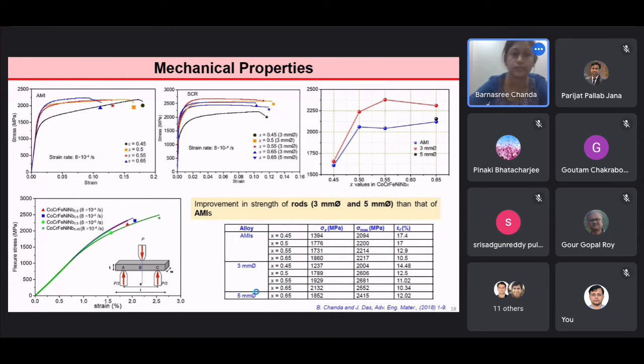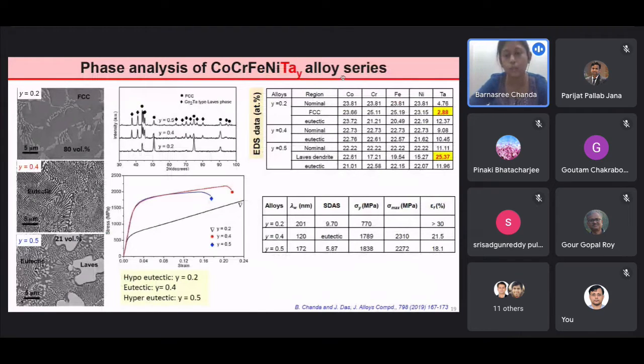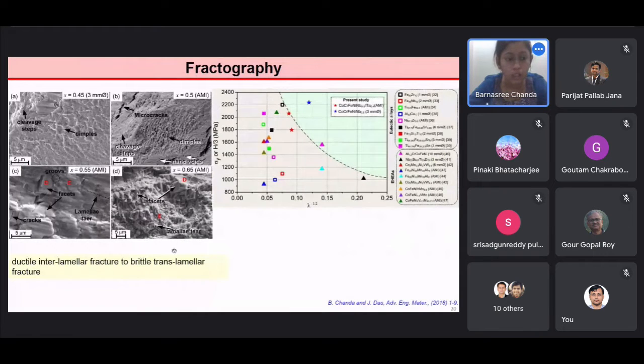Another alloy series has been developed, that is the cobalt, chromium, iron, nickel, and tantalum alloy series. At 0.2, there is 80 volume percent of the FCC phase. At 0.4, a fully eutectic microstructure can be seen. At 0.5, there are dendrites of Co2Ta type Laves phase. Also, due to the presence of a smaller volume percentage of tantalum, the yield strength is lowest in case of 0.2, and as the Laves dendrite volume fraction increases, the yield strength increases. The fractography shows a change from ductile interlamellar fracture to brittle translamellar fracture due to the presence of facets and cracks.